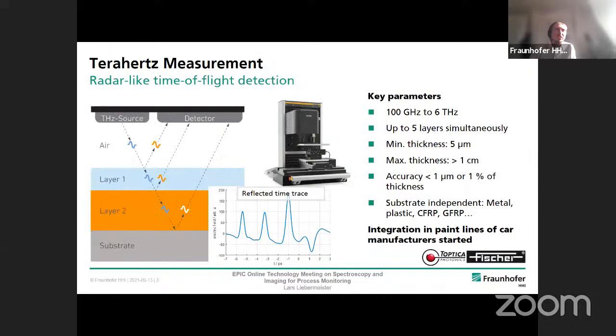And the process is the following. It's quite similar to what you might know from radar. So we send out, for example, a terahertz pulse, so an electromagnetic pulse in the terahertz frequency range, onto our layer structure. And then there will be a partial reflection at every interface between different layers. And with our detector, we can detect all those reflections. And because the frequencies are that high, in the terahertz range, we can distinguish the peaks from all those individual layers in the time of flight measurement.